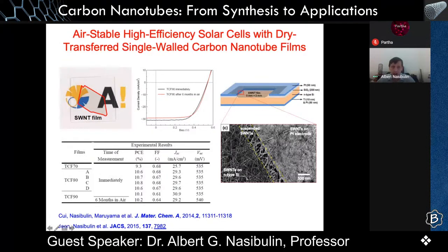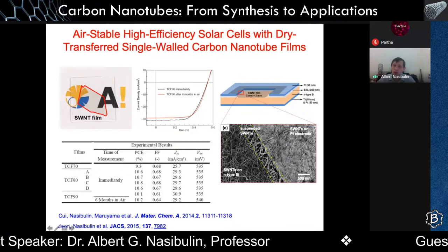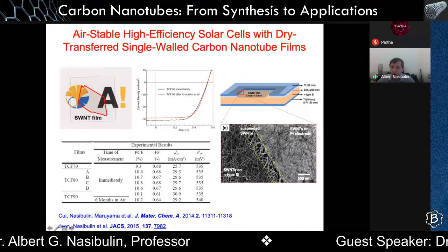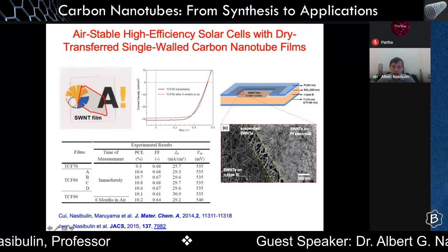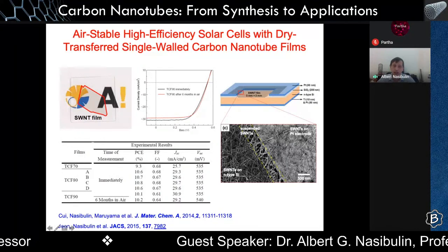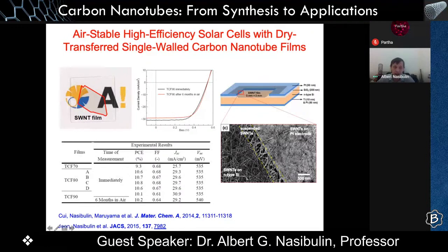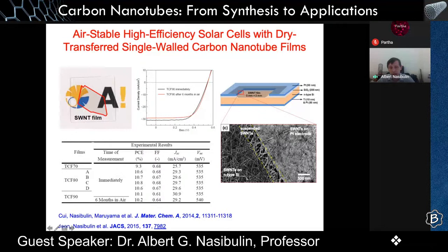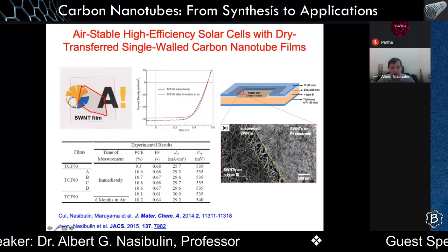What else can we do with transparent conductors? One of the applications is of course a solar cell. So back in 2014, we took N-doped silicon. This is a silicon substrate, and when we put a carbon nanotube and P-dope it, we get a PN junction. When you irradiate with the sun, this PN heterojunction basically starts to create photoelectricity, with an efficiency of about 10%, and after 6 months it is quite stable, and it works. That was done in collaboration with the University of Tokyo, Maruyama sensei.